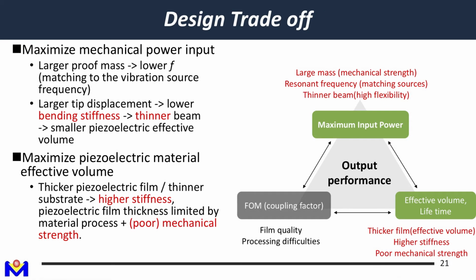Okay, so we have a design trade-off here between the mechanical input power and figure of merit of the material, and the piezoelectric effective volume. From the mechanical perspective, if we want to maximize the mechanical power, we can have a larger proof mass, but that induces a lower resonance frequency, and your resonance frequency has to match the vibration source frequency. We can also have a larger tip displacement. That means we have to lower the bending stiffness of the beam, which means an overall thinner beam. But again, that also changes the resonance frequency, so you have to do optimization. And you will also have a smaller piezoelectric effective volume.